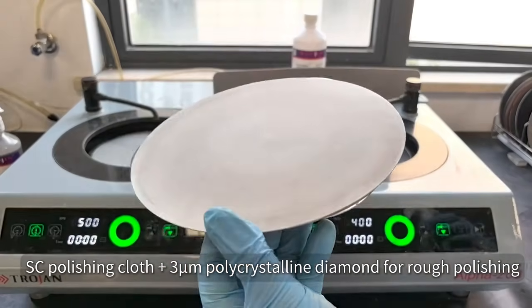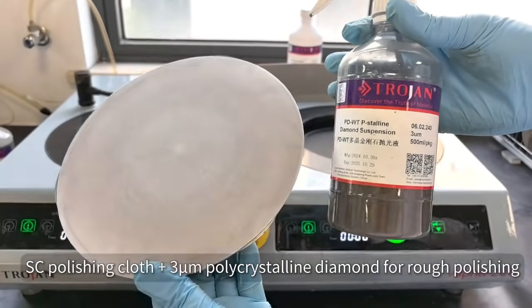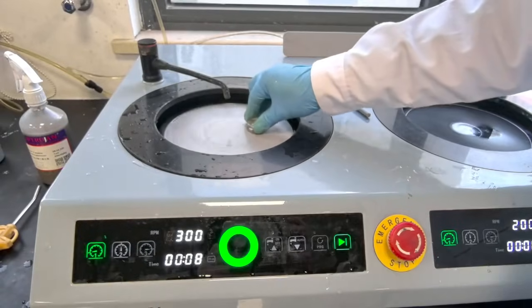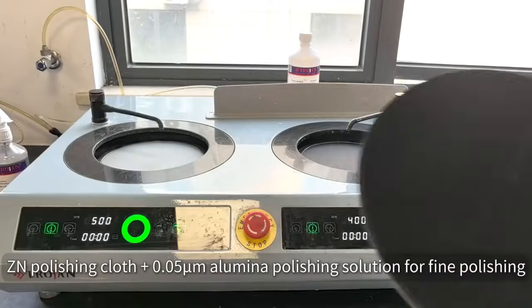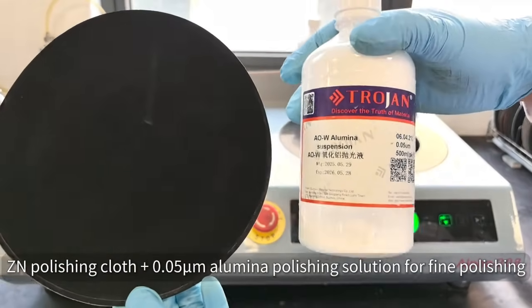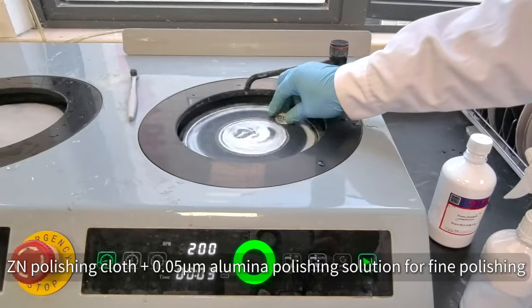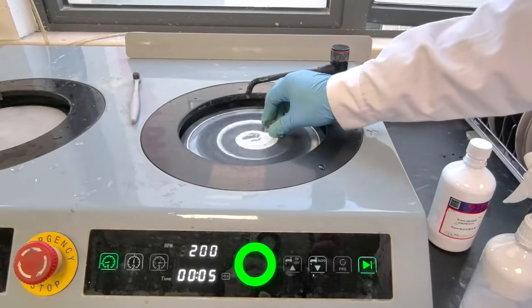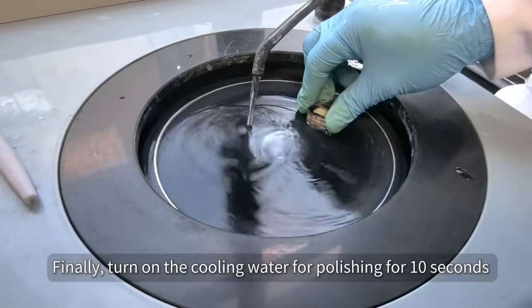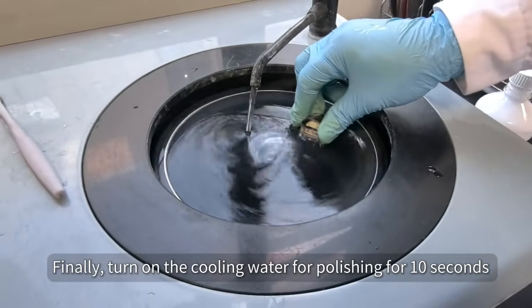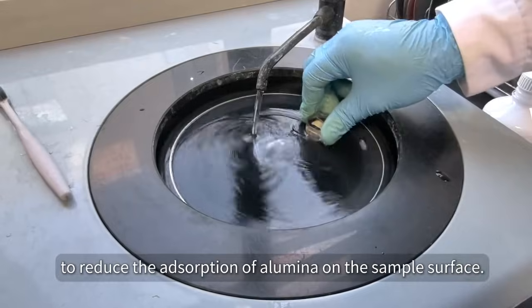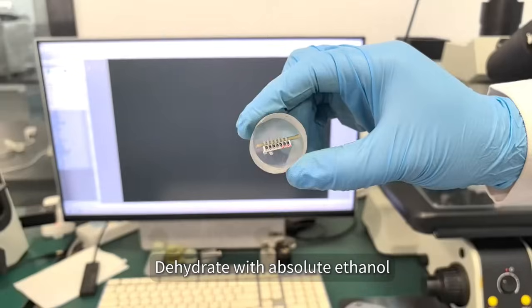SC polishing cloth plus 3 micrometers polycrystalline diamond for rough polishing. ZN polishing cloth plus 0.05 micrometers alumina polishing solution for fine polishing. Finally, turn on the cooling water for polishing for 10 seconds to reduce the adsorption of alumina on the sample surface. Dehydrate with absolute ethanol.